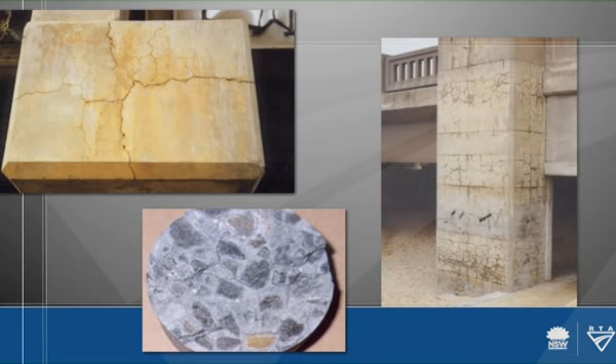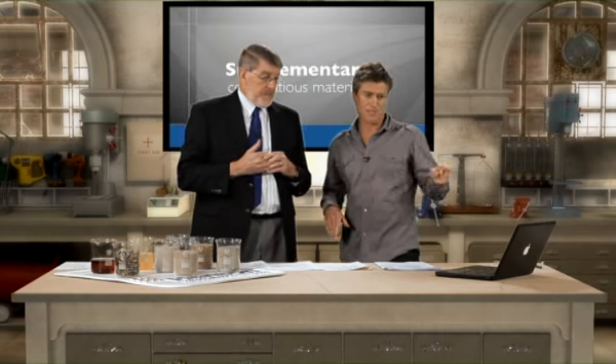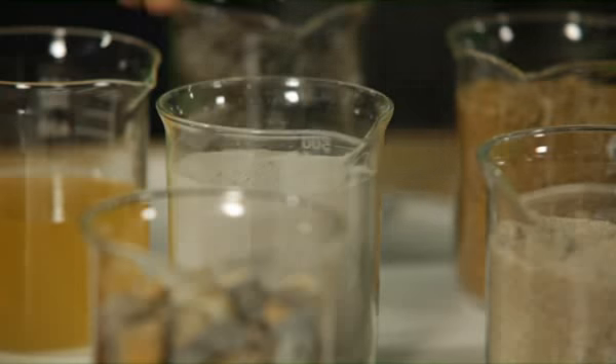And if you look at this section here of the concrete, you can see there's a piece of aggregate there with a distinct line around it, and that's the formation of the gel that will eventually damage the concrete. So to overcome the problem, all the aggregates now have been tested for reactivity to see whether they're susceptible to this problem. And so when a concrete mix is put together, they know whether they need to somehow address the problem. And that's where our supplementary cementitious materials come in, if I'm not mistaken. Yeah, and the actual material that's used is this material here, fly ash. And the beauty about the fly ash is that it's a recycled material, so there's a lot of it around.